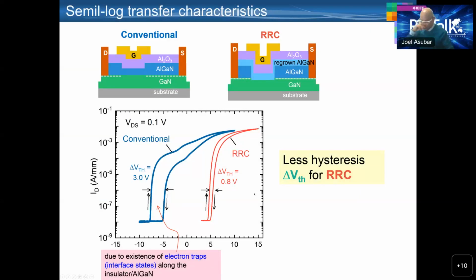Okay. So again, the question pertains to the subthreshold swing, which is regarding this portion of the transfer curves. The subthreshold swing is actually a measure of how fast or slow the device can be turned on and off. The subthreshold swing should be smaller. A smaller subthreshold swing means that the slope here is almost vertical, right? As you can see from this comparison of our conventional and recessed-gate HEMT, this slope of the subthreshold is much more vertical compared to the subthreshold slope of the conventional, meaning there are fewer interface states for our proposed device.